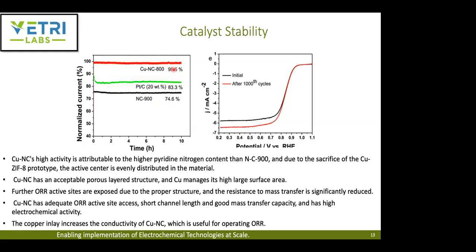And they also did this linear sweep voltammetry. So basically doing an accelerated stress test for 1,000 cycles at a very high scan rate between a potential of about 1.1 volts to about 0.6 volts with respect to RHE. And then they recorded the LSV. And maybe I think it's kind of like a mistake, I would say, something probably went wrong when plotting.